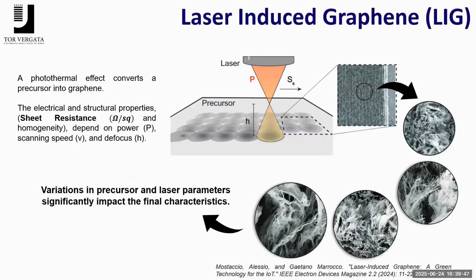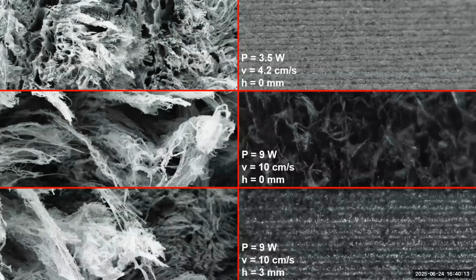Well, how can we fabricate this physical unclonable function? We can use laser-induced graphene. Laser-induced graphene is a process to fabricate graphene by using a laser that engraves a surface. When it engraves the surface, it will provide some fluffy graphene behavior, and the surface becomes rich in carbon. And the very important point is that we have many different settings, so that we can obtain different values of surface conductivity and different morphologies from one case to another, but also if we move from one place to another, we could have a different morphology. So this is the random behavior that we can use to extract information.